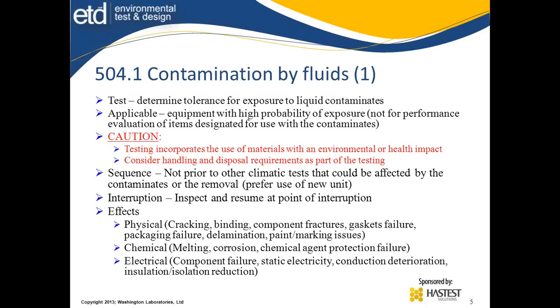Delamination, and this is really prone to displays that have a laminated or a conductive surface. Paint marking issues, you can't tell what button does what anymore, you lose its label. Labels of the product, operational parameters, things like that disappear. The chemical: you end up with melting, corrosion, chemical agent failure protection. Something is a problem here.